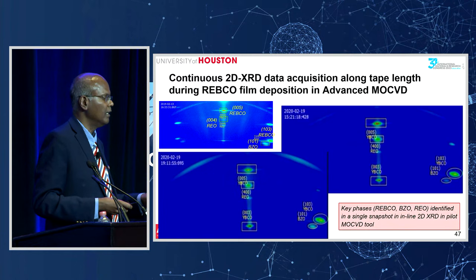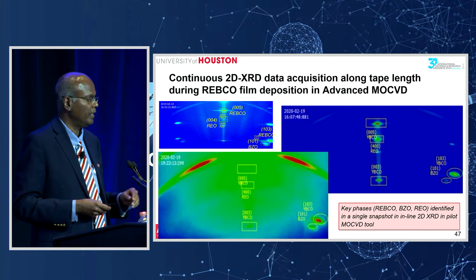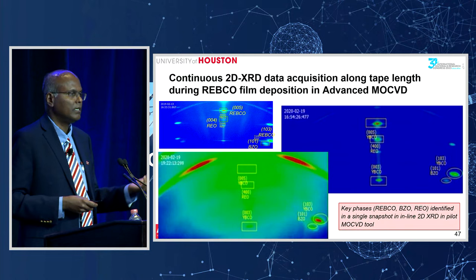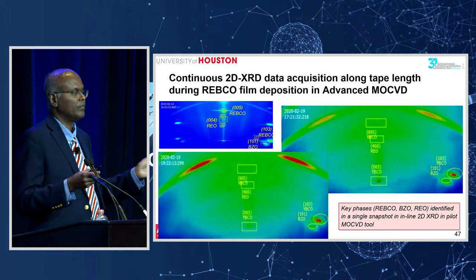You can see all the 00L peaks of the REBCO. You can see the BZO, the barium zirconate peak. You can see the REBCO 103 peak. You can see the rare earth oxide peak. So we can actually collect the intensity, the location, the spread, all the information, in real time as we're making the tape. So this data now can be compiled and you can look at it, right?